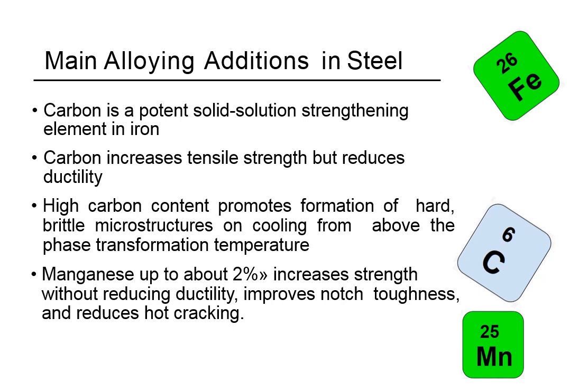High carbon content promotes formation of hard, brittle microstructures on cooling from above the phase transformation temperature. This gets back to Metallurgy 101, when we're talking about steel going through an allotropic phase transformation when it goes from body-centered cubic to face-centered cubic, back to body-centered cubic, and then into a liquid, and then cooling it all down really fast, and you end up with martensite, which is body-centered tetragonal. But anyways, the more carbon you put in there, and then you heat the material up above the phase transformation temperature, and then you cool it really quickly, all that carbon that was dissolved in solution doesn't have anywhere to go.